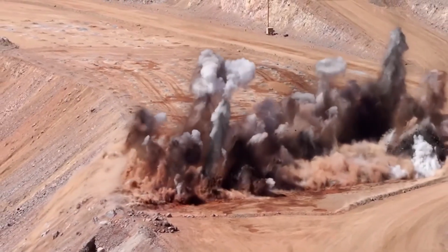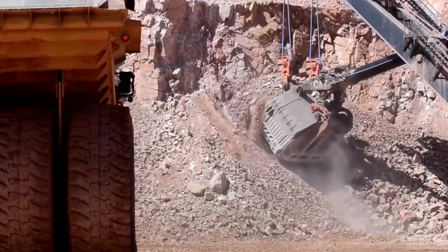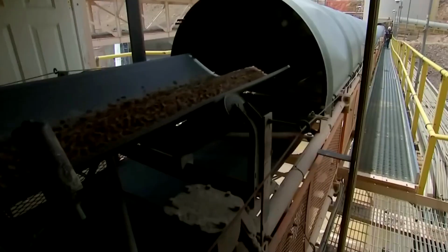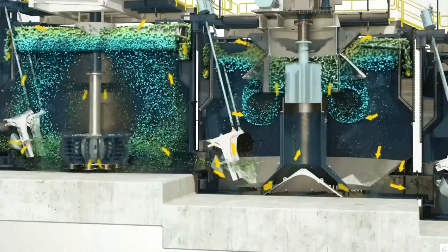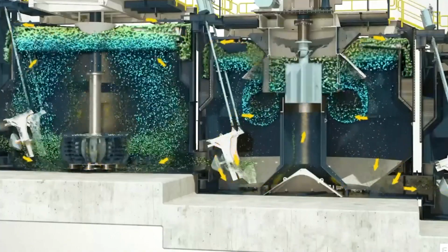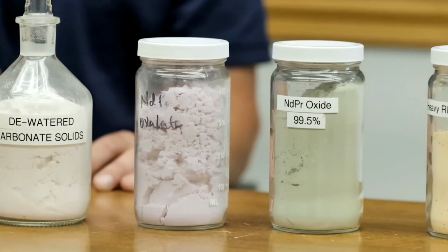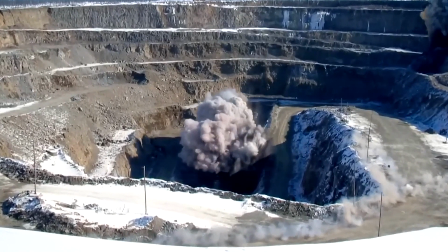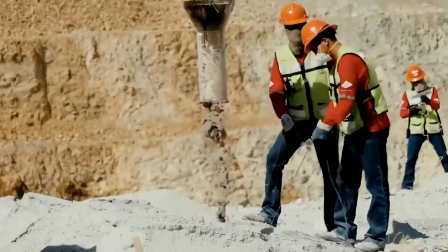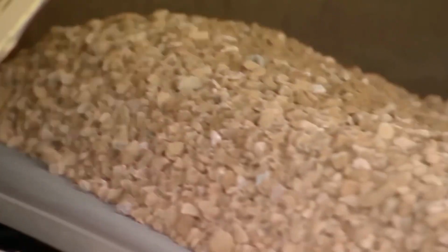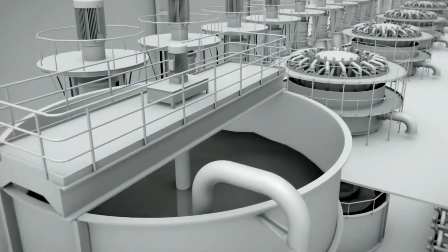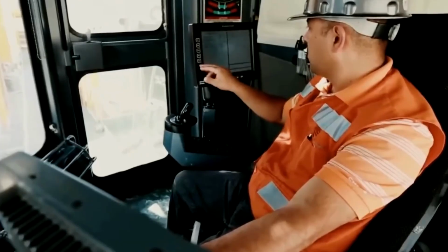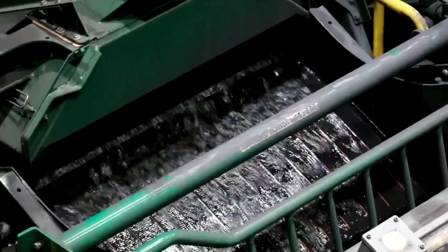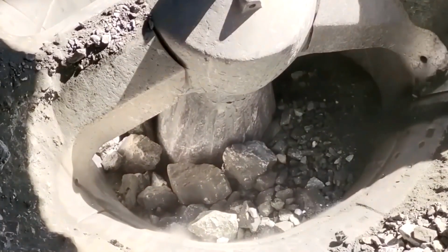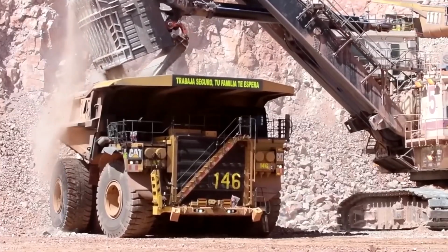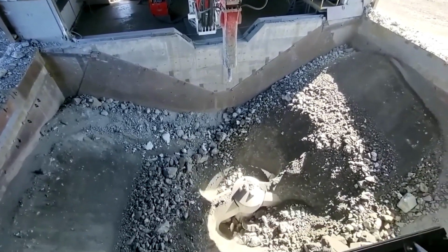This relentless process continues for 4 to 6 hours until the material is reduced to particles averaging just 3 to 10 microns in size. During the entire milling operation, the internal temperature of the grinding chamber is under constant watch, never allowed to exceed 180 degrees Fahrenheit. This critical control prevents any alteration of the ore's delicate crystal structure or the loss of its natural magnetic properties. Once the grinding is complete, the resulting powder is cooled with an inert gas. It is then passed through a multi-layer screening system, which precisely separates the particles according to their size, ensuring only the finest dust moves forward.